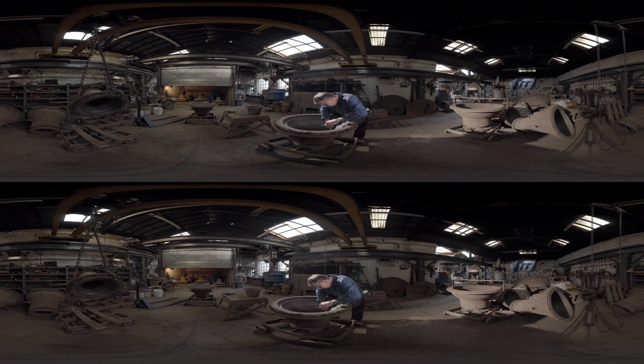The inside of the mould is lined with a moulding loam, which is a mixture of sand, clay, goat's hair, horse manure and water. And before the very last layer of loam is dried, lettering or decoration is tapped into the surface of that side loam, so that when the metal enters the mould, those features then stand out in relief on the surface of the bell skin.